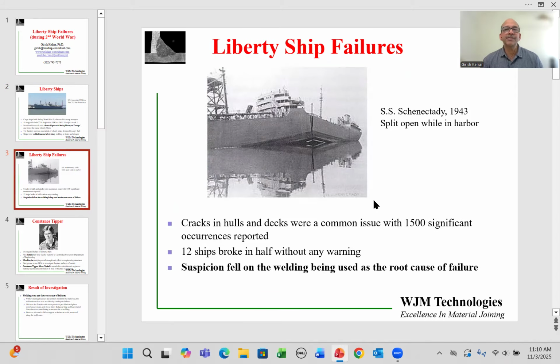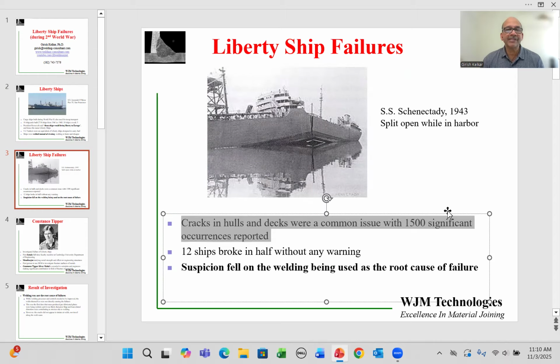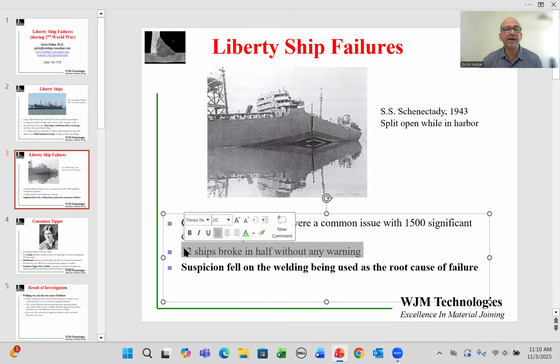Unfortunately, quite a few ships had issues. This photo shows the SS Schenectady, which just split open in 1943 while sitting in the harbor. Cracks in hulls and decks were a common issue, with 1,500 significant issues reported. And in some cases, up to 12 ships actually broke in half without any warning and sank, leading to a lot of loss of life.